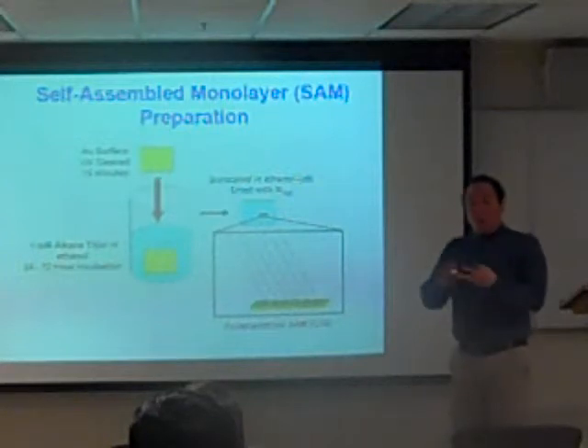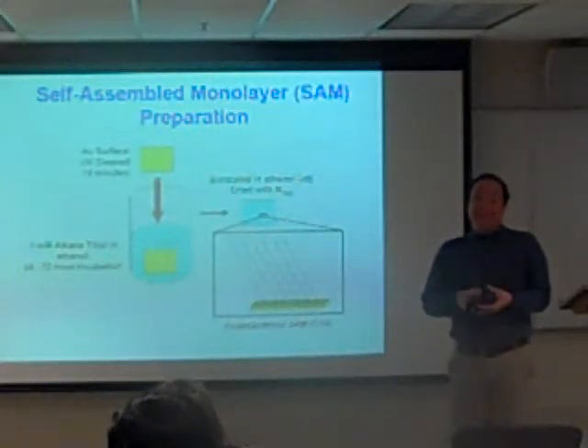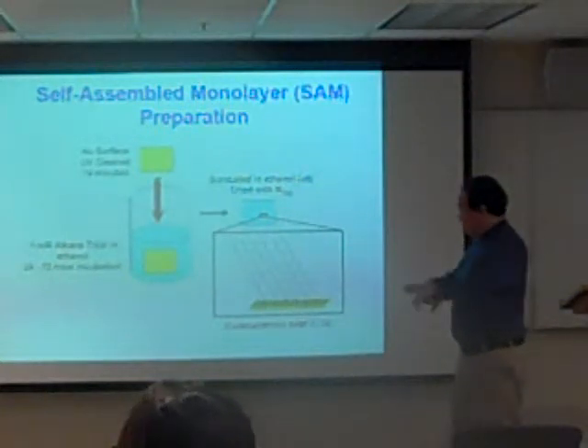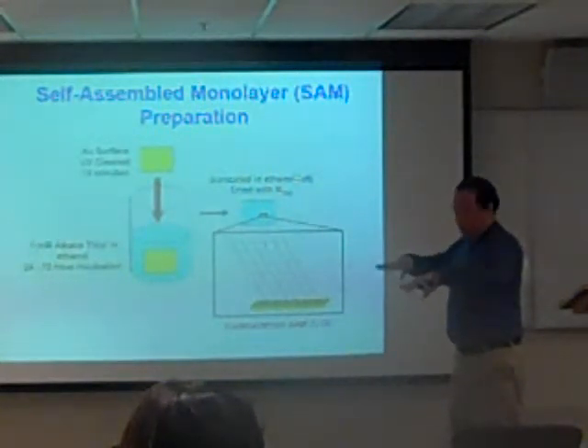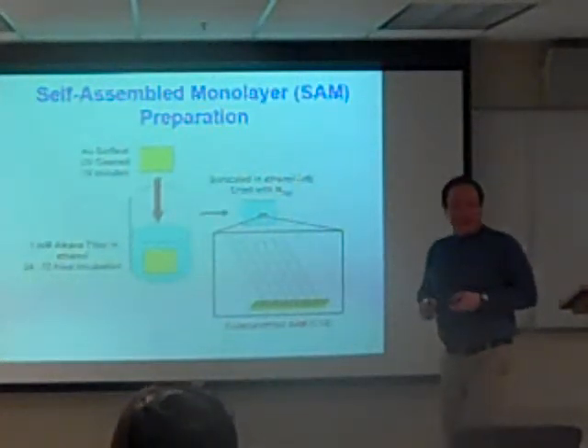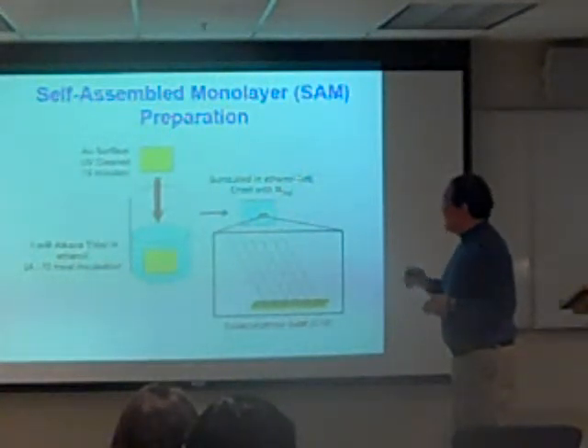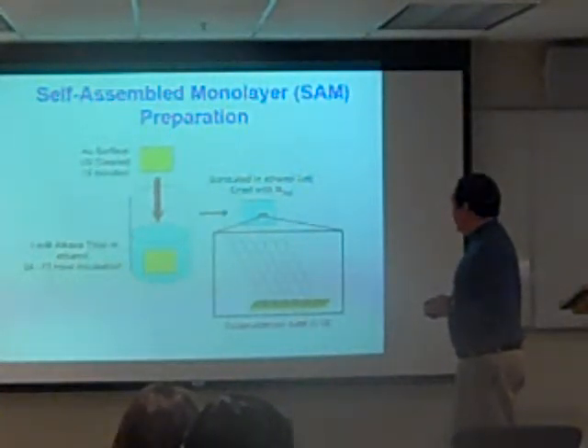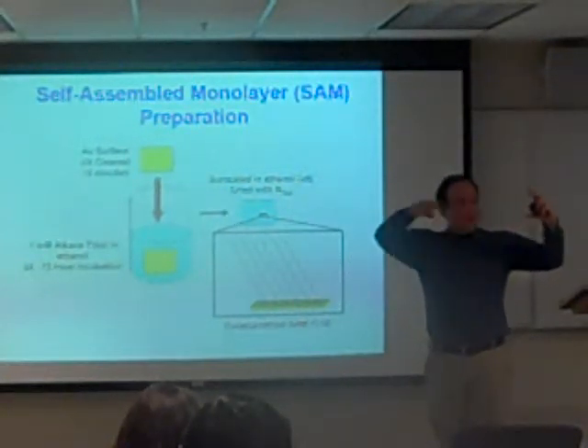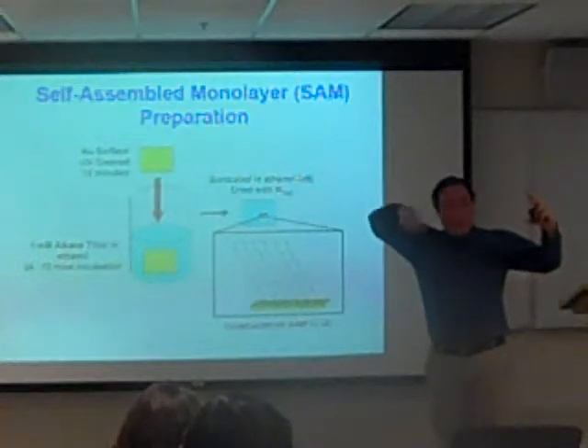So usually, we take a piece of gold, or gold that's been sputter deposited on, let's say, silica, like silicon 111, and then you get a gold surface. That's a cheap way to do it. Instead of getting gold itself, we just have it sputter coated. And then we can immerse it in an alkane thiol solution. Basically, it's just an organic chain with a sulfur here, lots of carbons, and then you can have your functional group of your choice.